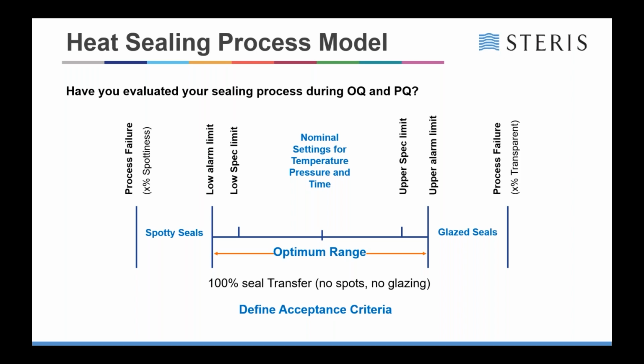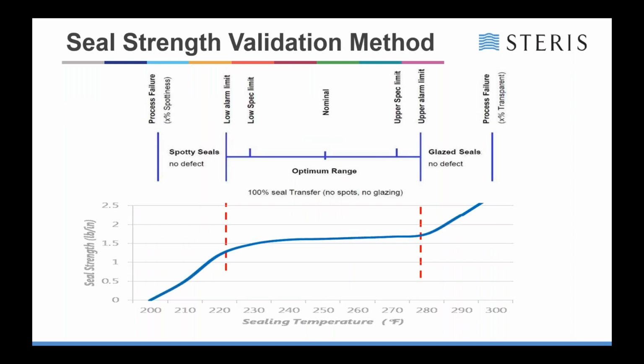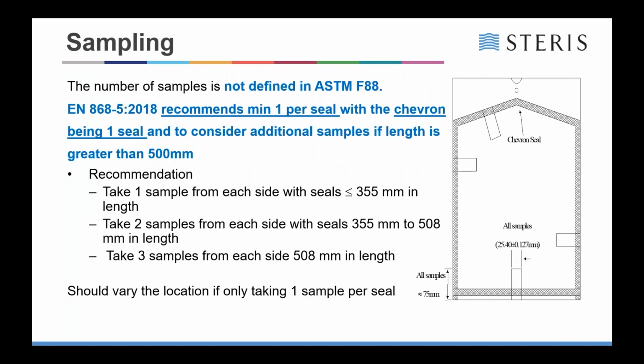If you're towards the spotty seal, this means that it's most likely going to be opened or very easily opened. If you're on the glazed side, it's going to be burnt and that will possibly crack open during the use of the actual pouch itself. Again, what you're looking for on the graph at the bottom here is the flat line area. You're trying to get someplace in the middle there. And that is an output from a seal strength evaluation that we did some years ago.